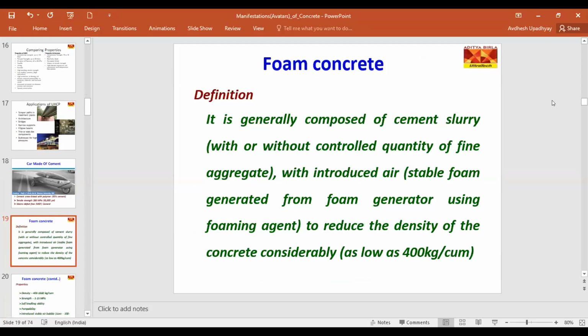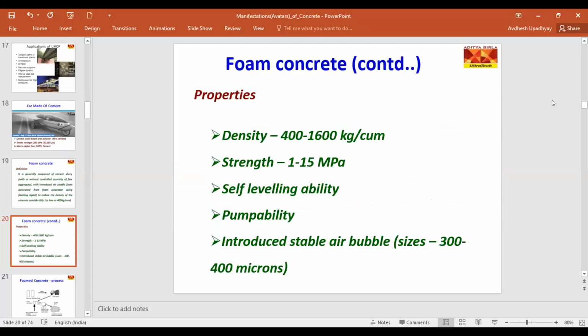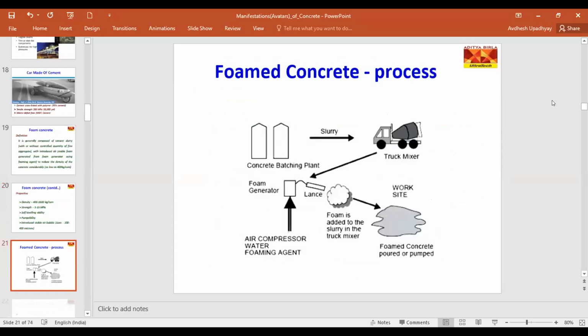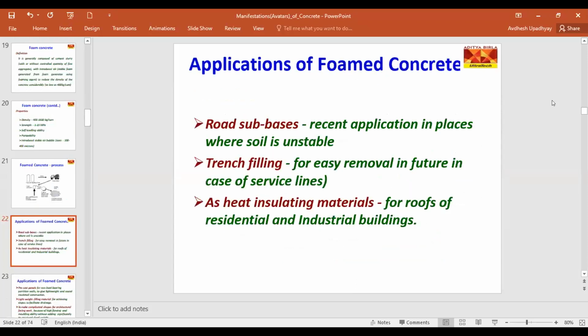What are the applications? First, these are the properties of foam concrete. Density ranges around 400 to 1600. Then strength is 1 to 15 MPa, self-leveling ability, pumpability, and introduced stable air bubbles. And the size of air bubbles is 300 to 400 microns. These are applications of foam concrete: road sub-bases, trench filling, and as heat insulating material for roofs of residential and industrial buildings.